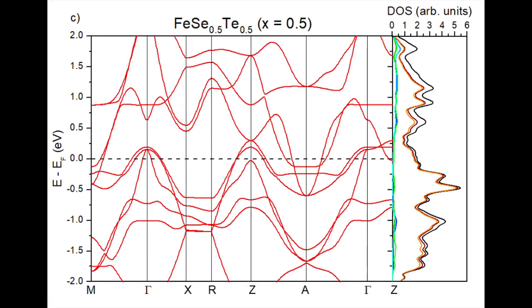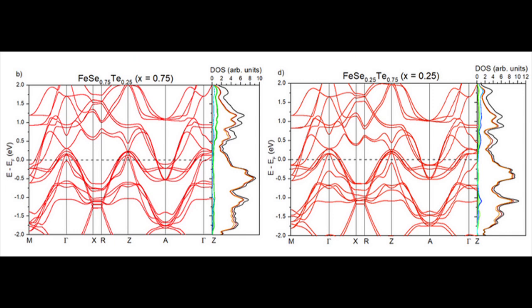Graph C shows an intermediate case, X equals 0.5, a compound with an atom of selenium and an atom of tellurium for each 2 atoms of iron. Here, we observe a change of density of states near the Fermi level, and the breaking of degeneracy is seen at the gamma point. These systems are comparable since the unit cell has the same structure and quantity of atoms, and these were not duplicated like cases X equals 0.25 and X equals 0.75 in graphs B and D respectively, which are systems built through cell duplication. This is reflected in the folding of bands. This can be seen at the gamma point with the apparent vanishing of the gap between states.